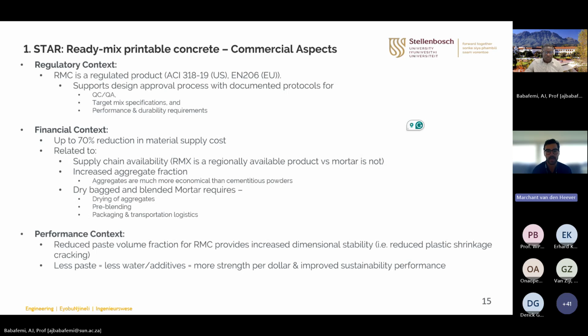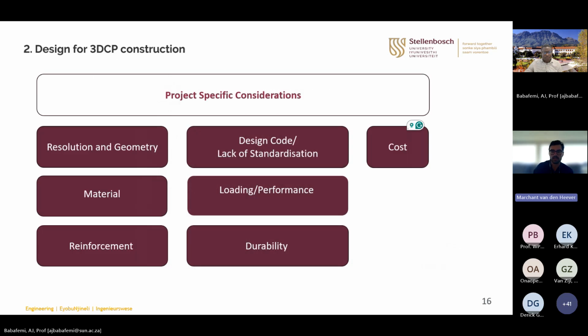But quite interestingly, from a performance context, we're able to reduce the paste volume fraction for these ready-mix materials, which provides increased dimensional stability. So it allows us to reduce the plastic shrinkage potential of these materials and mitigate the adverse effects of plastic shrinkage cracking. And basically what it boils down to is less paste means we need less water and/or additives to get the desired workability properties, which means that we get more strength per dollar and improved sustainability performance. So this is the reason why we in the industry very much prefer to work with a ready-mix printable material. John, if you could please move to the next slide.